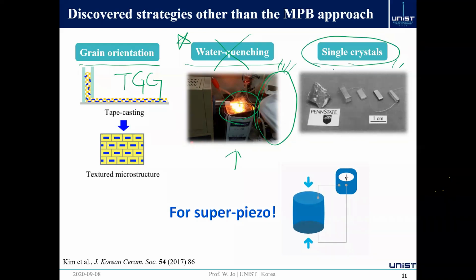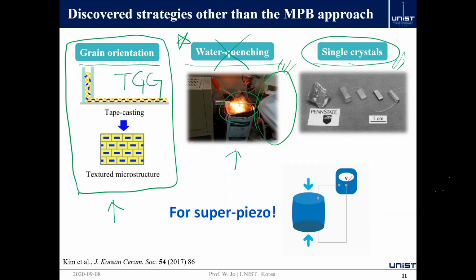And a single crystal, as I already told you, is too expensive, and the composition is not really reliable because it changes a lot from fabrication method to fabrication method. So in our lab, we are focusing highly on the grain orientation technique here, TGG. After this slide, what I want to show you is one of the examples of how we utilize this technique to make a new type of lead-free piezoceramics.